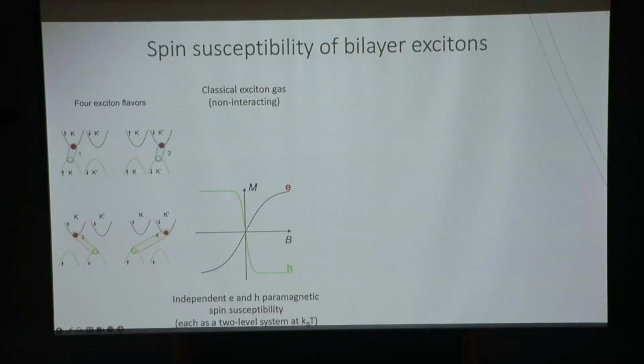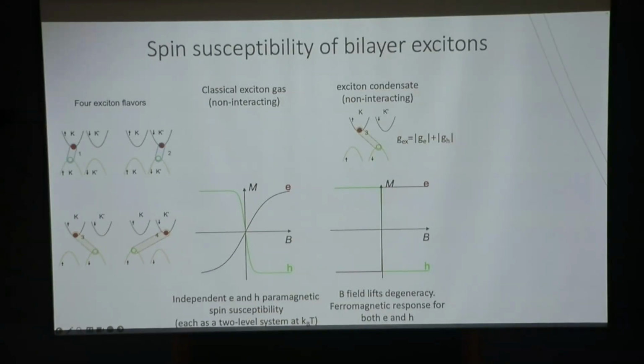Now, let's see what will happen in the quantum regime. If you have an exciton condensate, and assume they have minimum interactions, then even if these four states are initially degenerate, applying a very small magnetic field will break the degeneracy, because this state will have a larger g factor than these intravalley excitons. So this one will have slightly lower energy, even at minimum magnetic field, compared with the other three states.